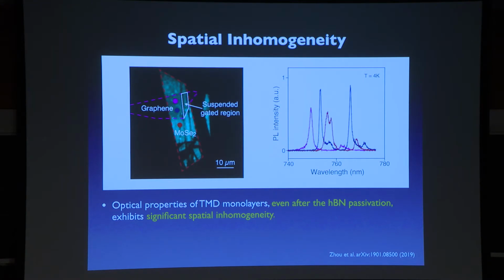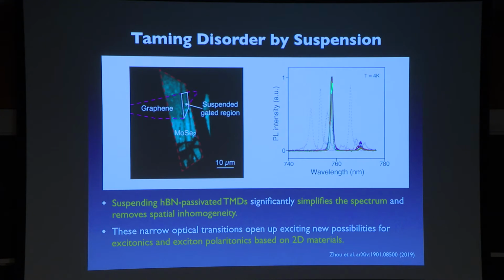But if you suspend them, then what you get are these lines. Wherever you measure in this suspended region, all the spectral lines overlap, which means that whatever you're measuring is intrinsic to the materials, and they are spectrally and spatially homogeneous. And then, as I will show you later, these lines are, in fact, as sharp as they can be. They are entirely lifetime broadened, if you like that jargon.